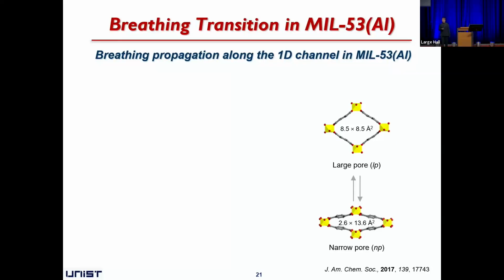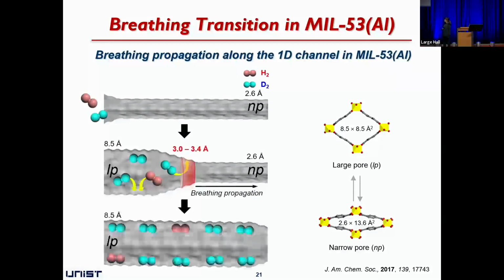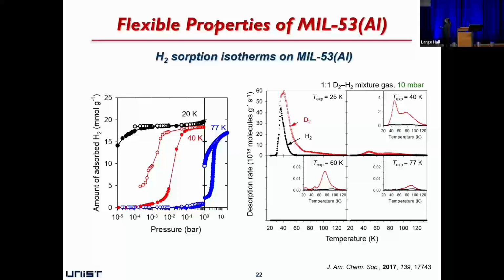So here, our hypothesis is that during the breathing propagation, at some point, it should meet 3 to 3.4 angstrom during the breathing transition. So we try to use this breathing transition to see the kinetic quantum sieving effect. As you can see here, from the hydrogen adsorption isotherm, we can see the beautiful breathing phenomenon. At low temperature and very low pressure, it is already in the large pore structure. But at 40K, around 10 millibar, we can see the breathing transition. So this is the right condition to see the kinetic quantum sieving effect.